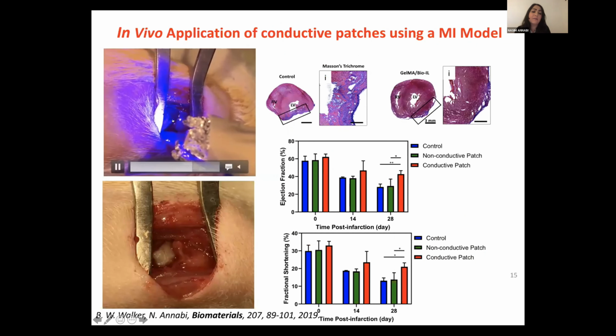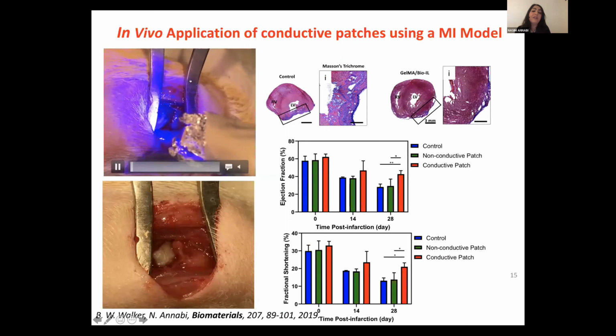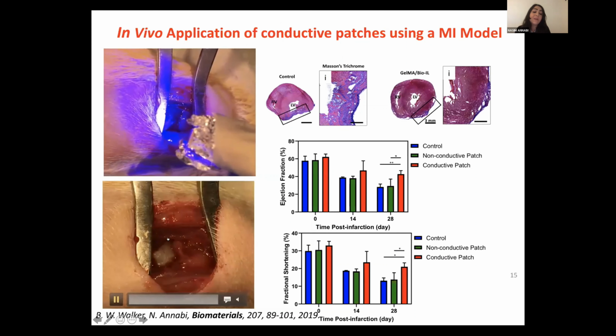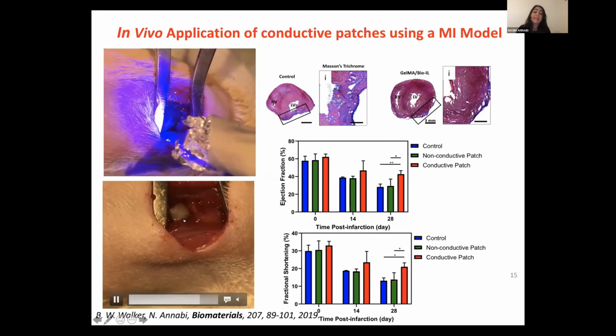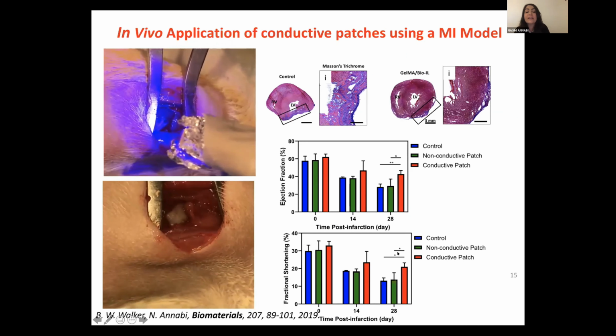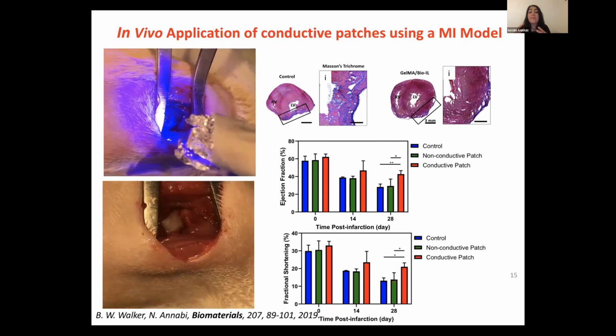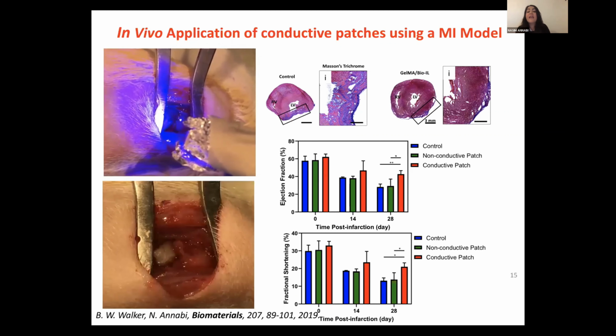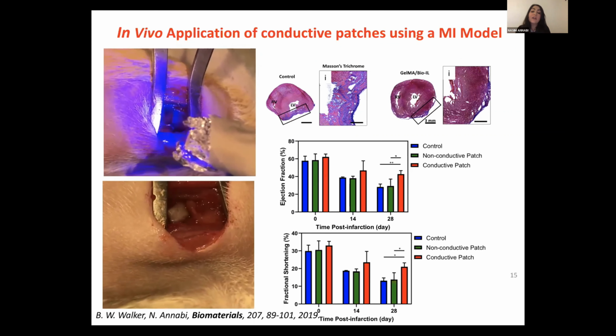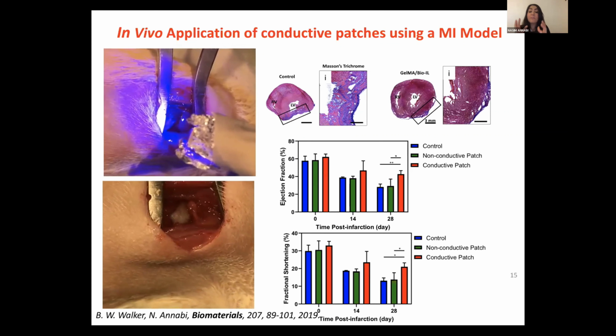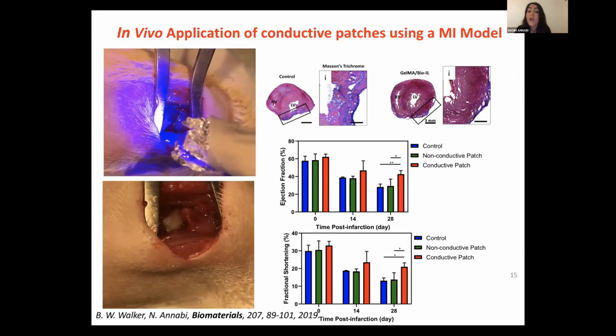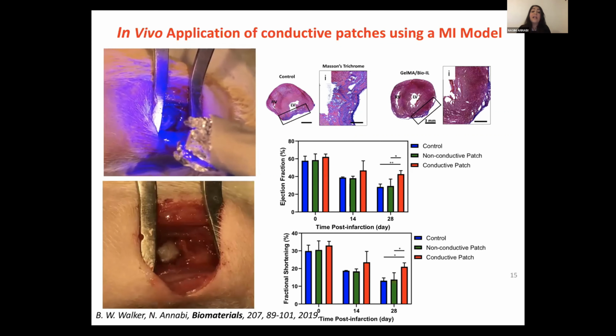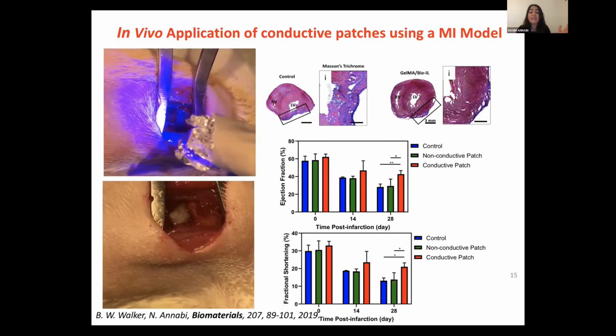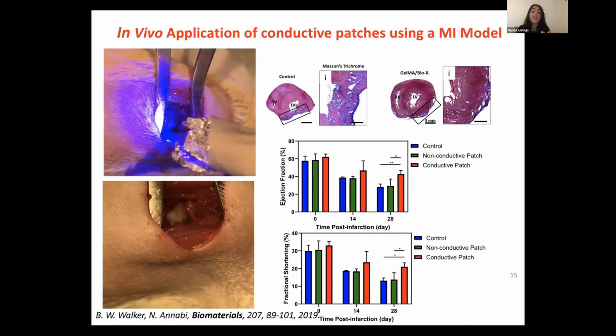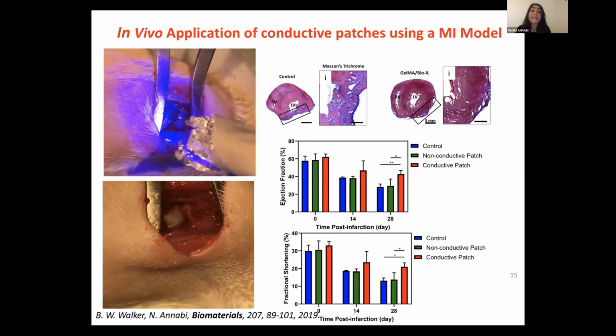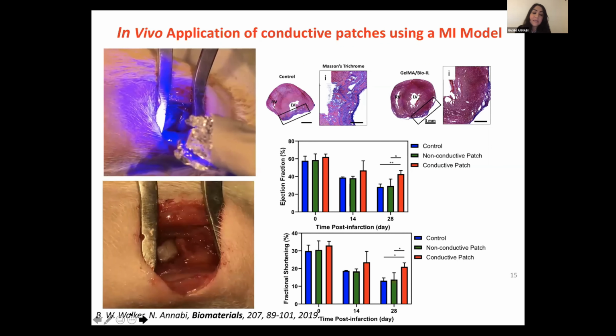And this is the rat heart. We put the patch, we photopolymerize it with visible light, and in this video you see the patch after 3 weeks it remains stable on the surface of the heart. And with our functional data, we show that as we treat the heart post-MI with conductive patches, we have better heart function compared to the non-conductive patches that we use for this experiment. These are some preliminary data, but now in collaboration with Professor Ardehali at UCLA, we are trying to do a larger scale in vivo test to understand exactly what is the effect of electroconductivity once we implant these samples in animals.